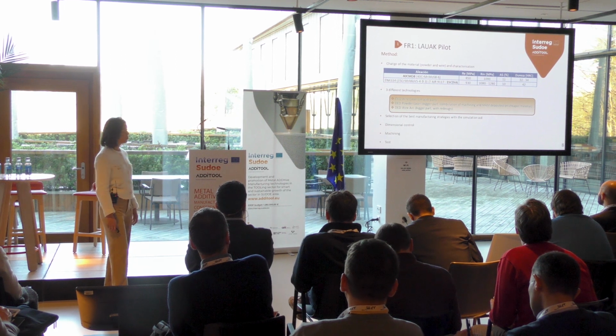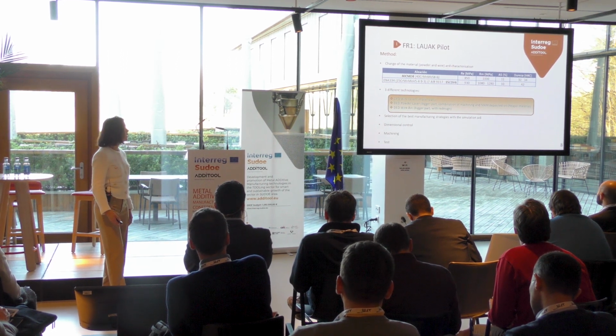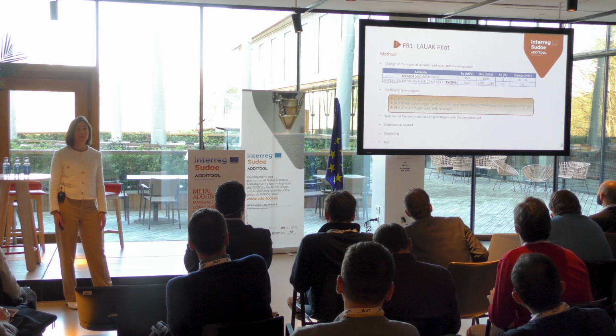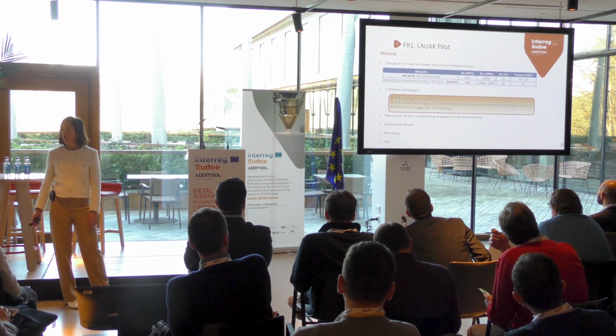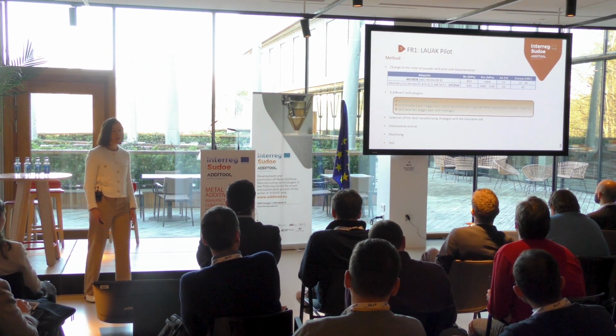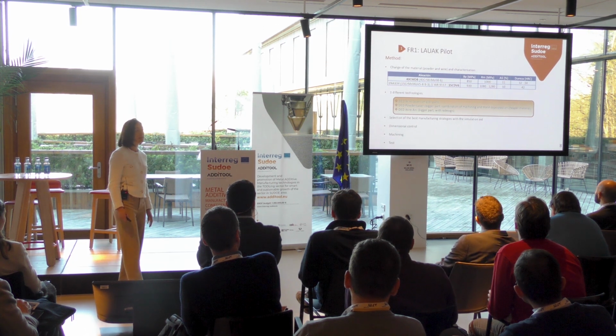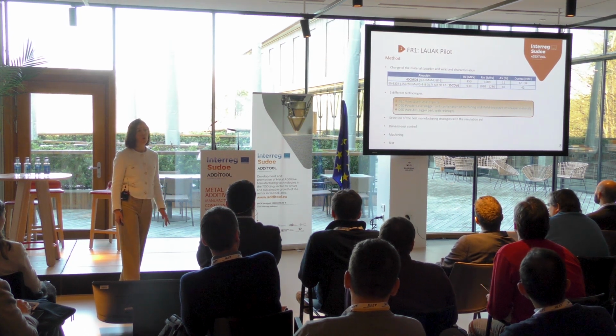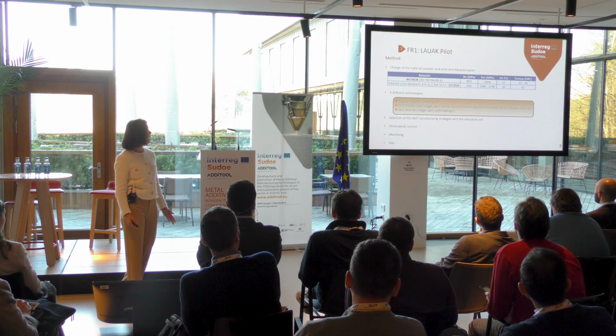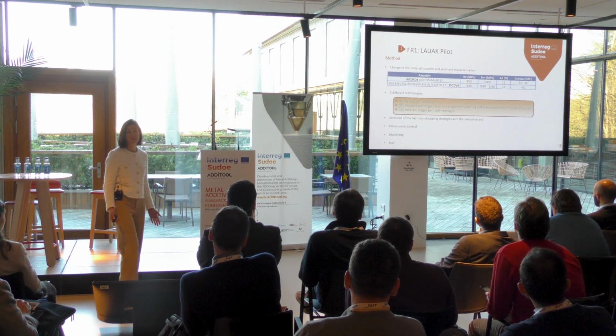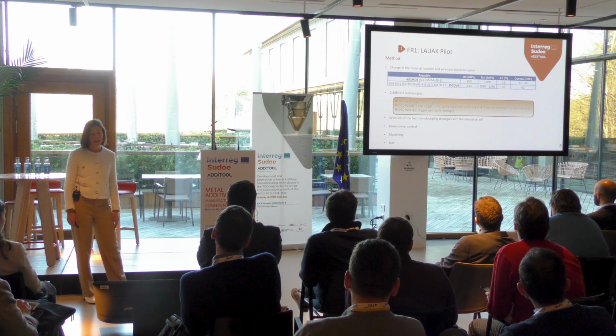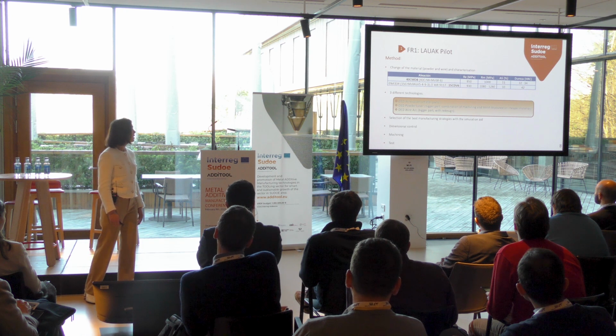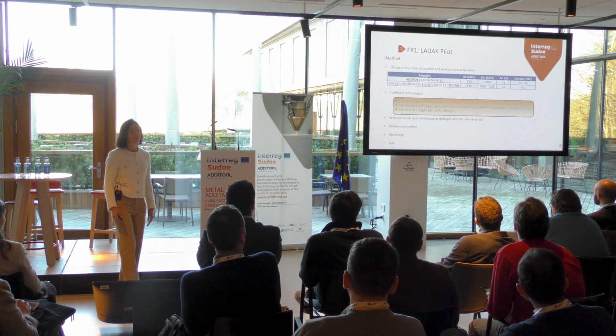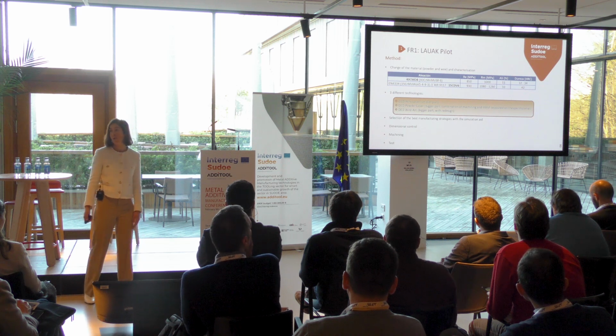We used DED wire laser for the smaller part, and DED powder laser for the bigger part. In this case, the material was applied on top of a base made by machining with a cheaper material. And finally, DED wire arc for the full big part, applying a previous redesign.